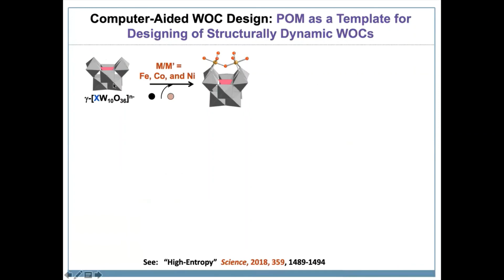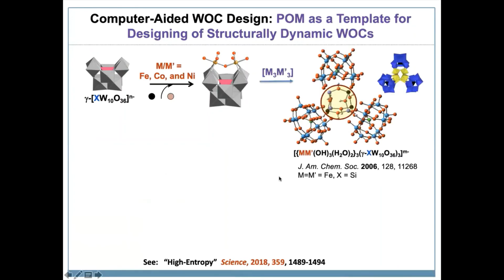We use polyoxometalate as a template to build a structurally dynamic photooxidation catalyst. You remember in photosynthesis, the active site is manganese-4-calcium cluster. It is not stable. It does the electron reaction, then destroys itself. After the reaction is done, it repairs. There is a repair mechanism. We want to mimic that. We have done this actually.